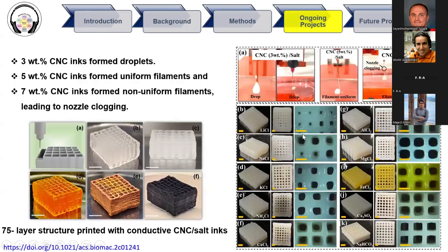And also, here we can see how Na can act as a bridge between these fibers. Finally, as we can see in this slide, by using different salts, from LiCl as the first one to sodium bicarbonate as the last one, we can see how these salts affect the printing quality. All of these samples had the same designed shape by Katia, but whenever we printed these samples, we can see in this picture that we have different quality. One step back, before adding salt, we had 3, 5, and 7 weight percentage of CNC, cellulose nanocrystal. Just have a look at the right picture A, please.